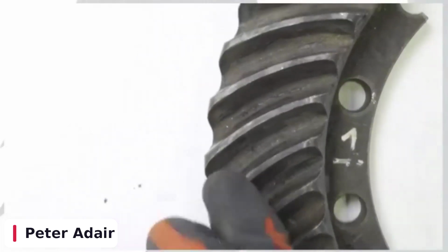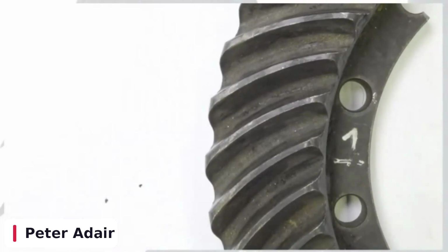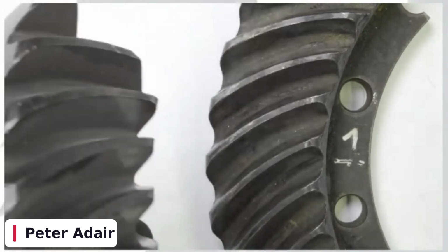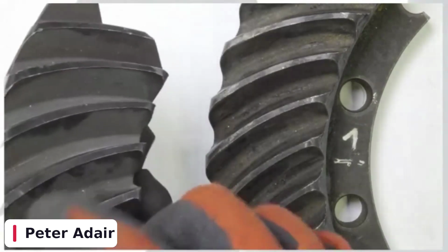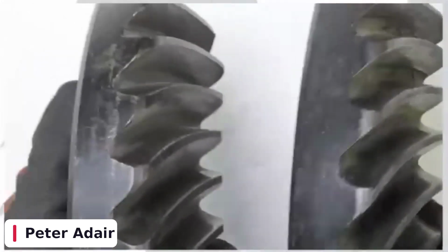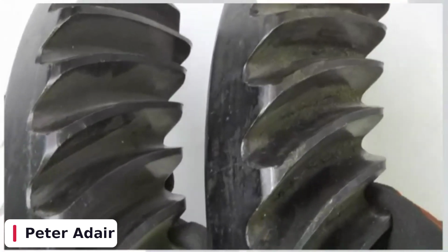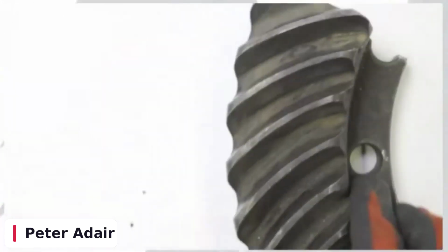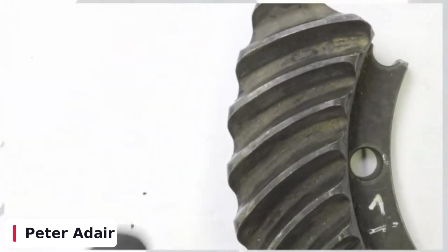So when we look at the two pieces side by side, this one has no carbon coking down on the inside, where this one's full of burnt oil and lube and has bluing. So again, wrong and low. Carbon coking is going to be a huge thing to look for. If you have burnt oil, you already know that you are in the position of low lubricant.